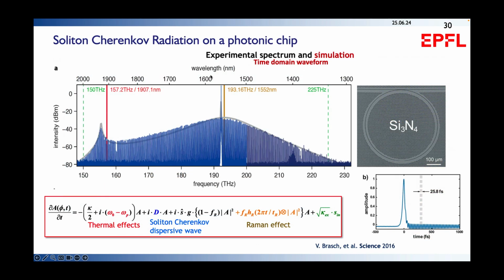Now, the next question is, can you generate actually these dissipative Kerr solitons also on this new platform of silicon nitride? And so this is an example of some of the early work where we demonstrated that it's possible to generate Kerr frequency combs in silicon nitride. And what's striking in silicon nitride is the vast bandwidth that we can generate. We can generate spectra that are octave-spanning. We can cover the entire telecommunications band, but the mode spacing here is very high. We can have mode spacings of 10 to even 100 gigahertz or even more. And we can model actually these based on this nonlinear dissipative Schrödinger equation. Inside the pulse, you have solitons locked to a background, which can also be very short. In this case, actually, it's a pulse that's about 25 femtoseconds.